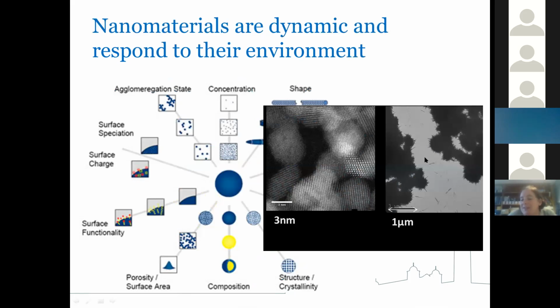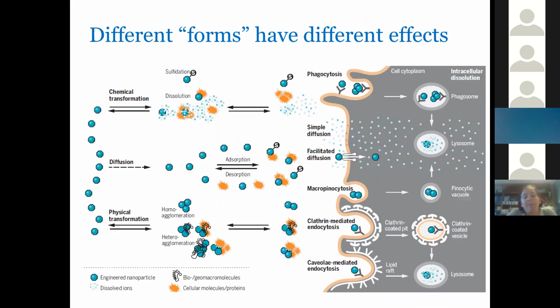And these spikes on these larger particles could, for example, puncture cell membranes or lead to things like frustrated phagocytosis, where if a cell is trying to take them up, attaching onto one of the narrower parts, it isn't able to fully engulf the rest of the particle. This is a process that happens quite frequently with carbon nanotubes or long rod-like and wire-like particles, where the cell is not able to take in the whole particle, but keeps releasing the inflammatory markers that tell it should be doing this. So this dynamic nature of nanomaterials means that they transform very much and very quickly, and the different forms will all have different effects.